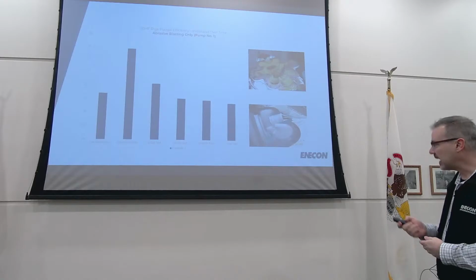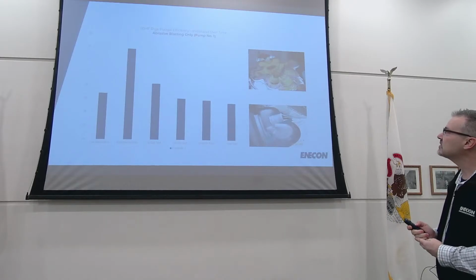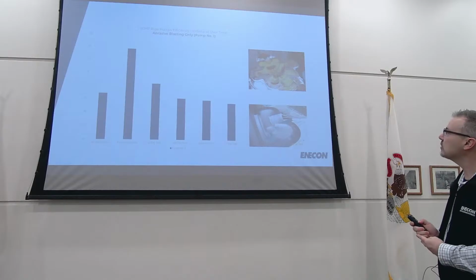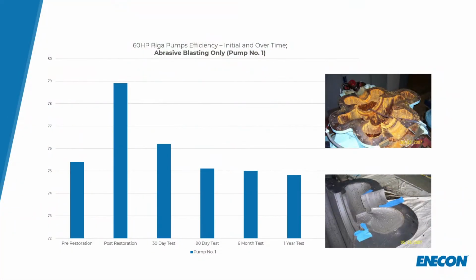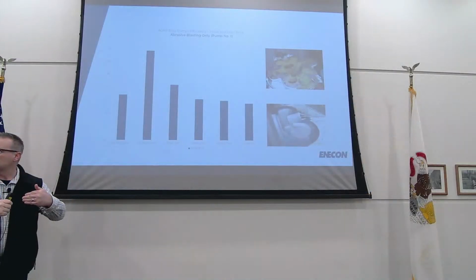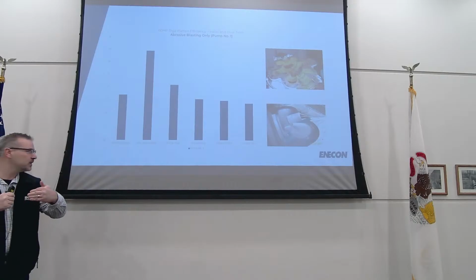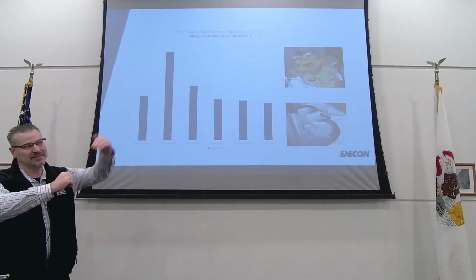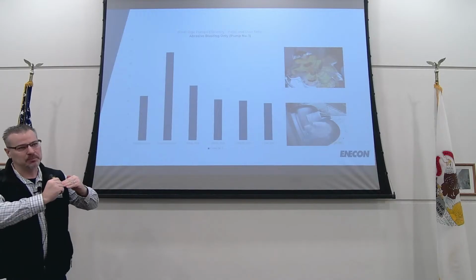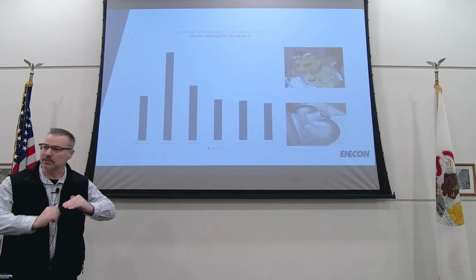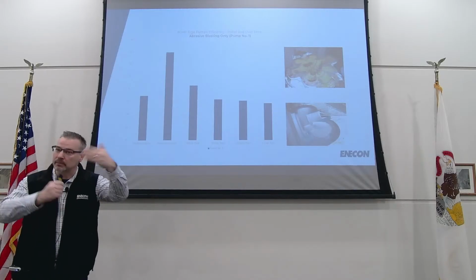So this is a pretty eye-opening slide right here. This one has a 60 horsepower pump, and this is the initial and over time. So in this case, they just did some mechanical refurbishment, did some seals, did some wear rings, and they wanted to see what that was going to look like with the blasting. So I'll actually come over here so you can see this. It starts up at 80%, it goes down to 72. Well, we're seeing it on a lot of new pumps, and you put these in, your efficiencies go down to what that manufacturer curve is relatively fast. So it might be in, and it might go down. Let's say you're at 90%. Pretty fast, you're going to be down to about 80% or so. And after time, you're going to be down to 60% of what that manufacturer's initial curve is.